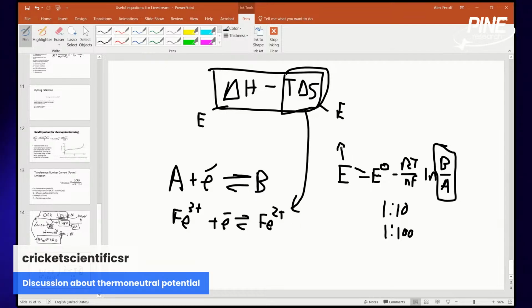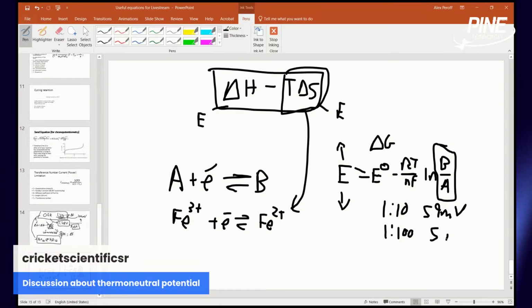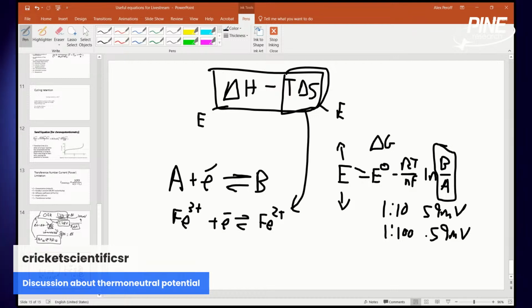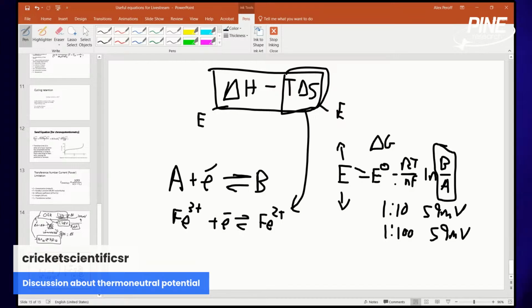But when you move away from the Gibbs free energy, delta G, in any direction and change that ratio, you're making the system, quote, more ordered. You're going from 2 species more to more like 1 species. And this has a 59 millivolt, I don't want to call it penalty, but penalty. You must go beyond the thermodynamic potential to drive the ratio of these 2 species by some amount. And so that's another level of thinking of this. It's like, oh, well, these don't change that much. This is pure Nernstian. That's a way to think about overpotential.